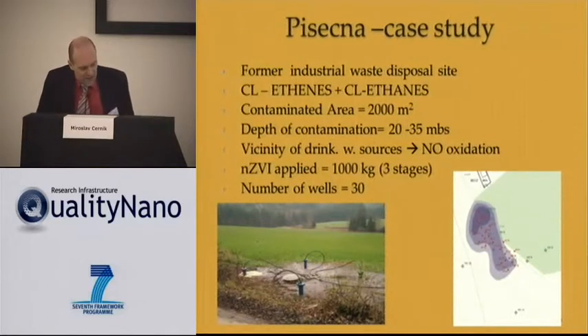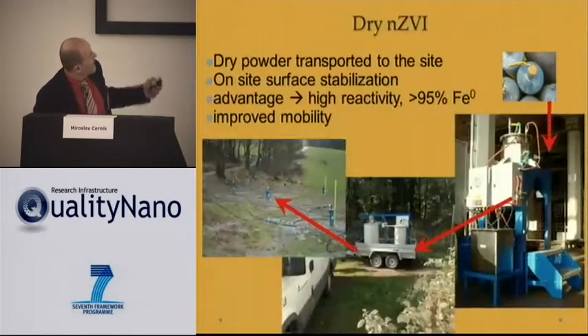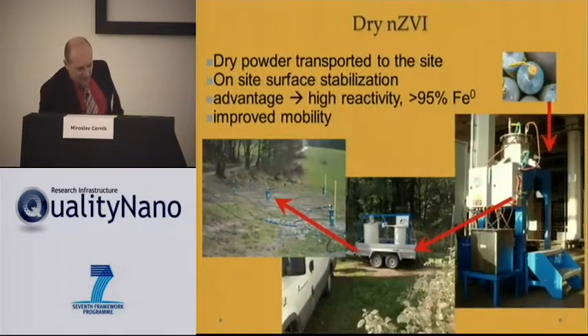This is the site called Písečná in the Czech Republic, which is a former industrial waste disposal site, contaminated by chlorinated ethenes and ethanes. The area of contamination is not so large, it's about 2,000 square meters, but the contamination is at a depth below 20 meters, and in the vicinity is a source of drinking water, so it is not possible to use some aggressive method like chemical oxidation, for example. We applied nanoparticles in an amount of about 1 ton in 3 stages to 30 wells, and I will show you the results.